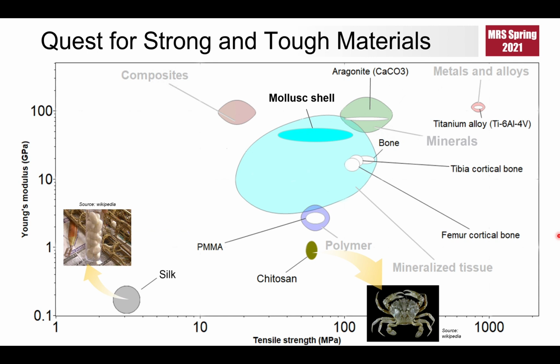Bio-based materials such as chitosan, one of the most abundantly available polymers, but as shown in the modulus versus tensile strength plot here, the mechanical properties of chitosan are lower than most conventional materials. To pursue load-bearing applications, it's inevitable to improve the mechanical properties of chitosan.